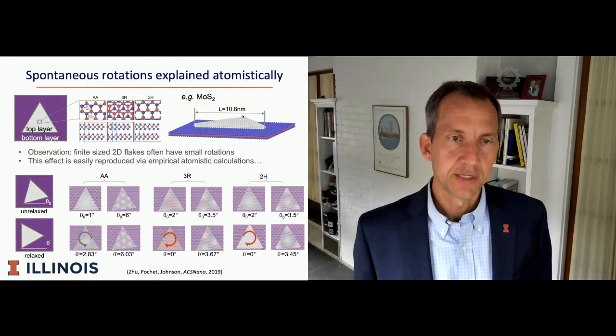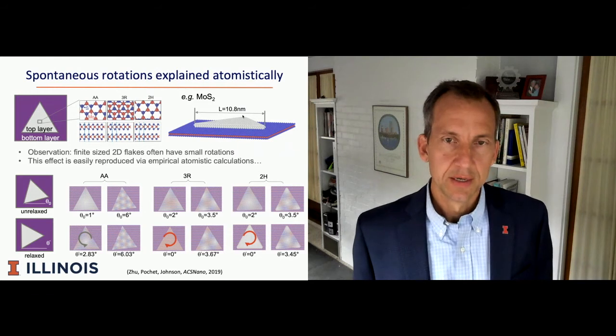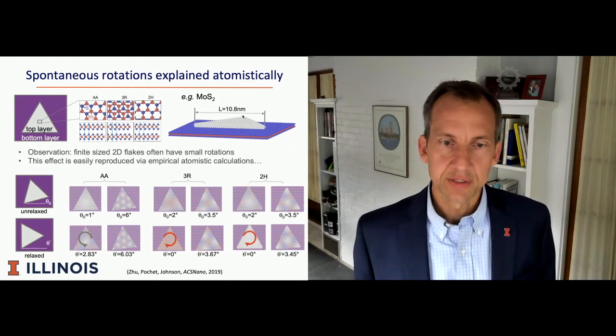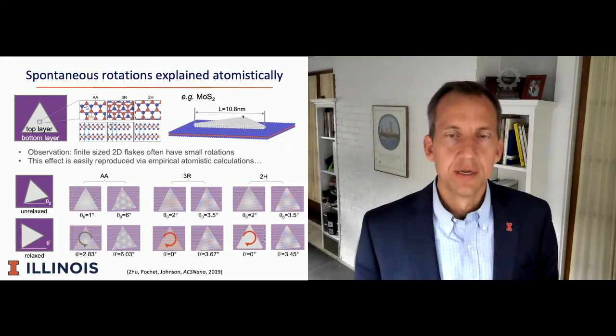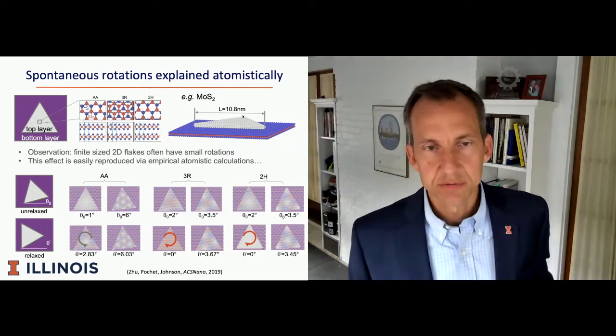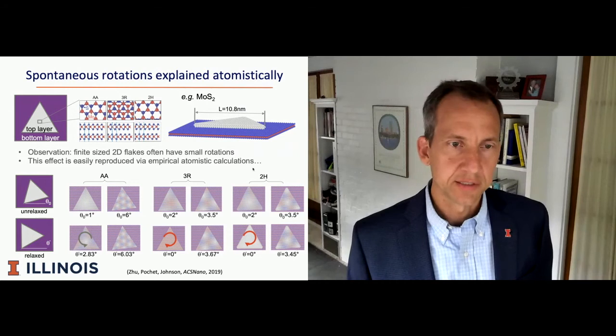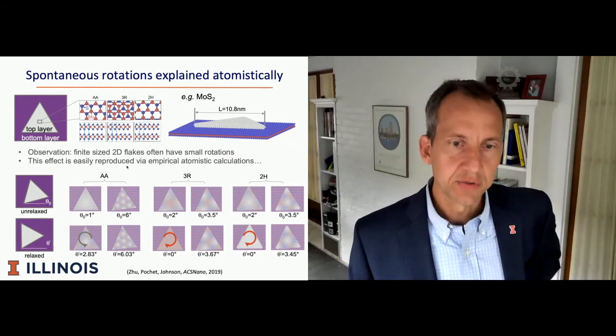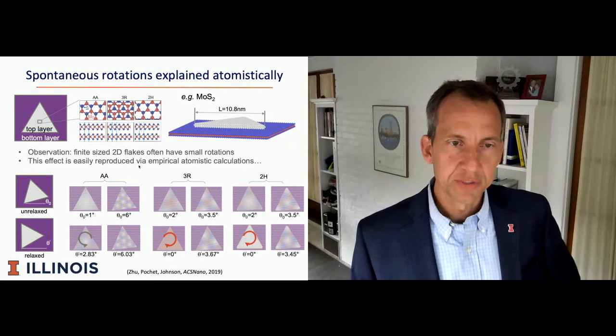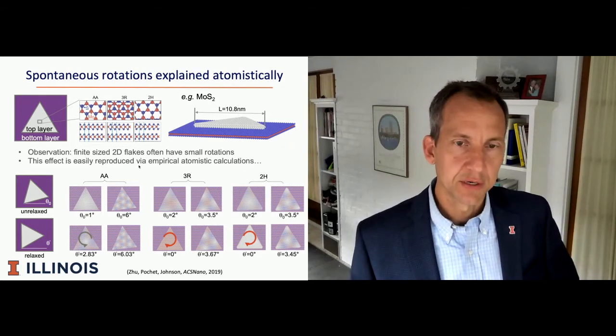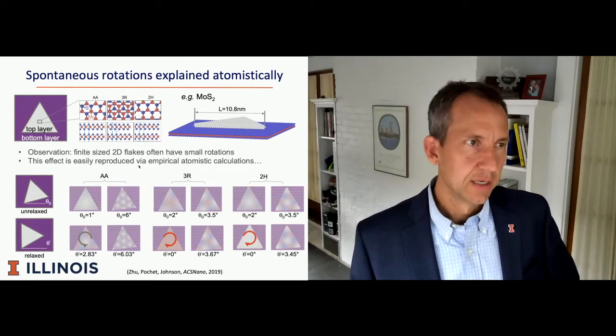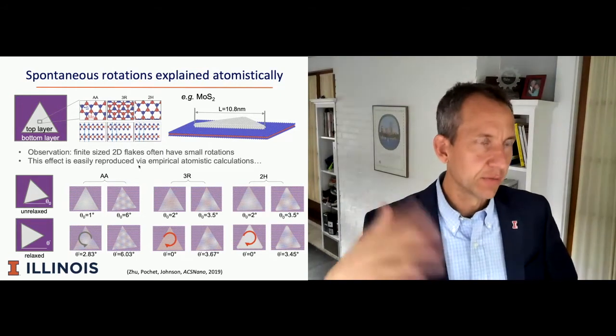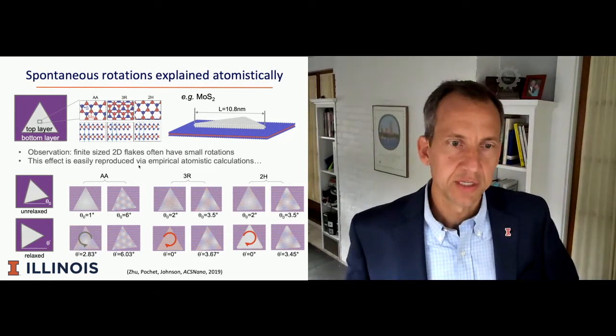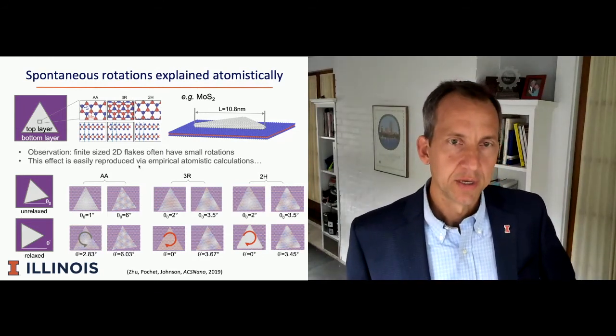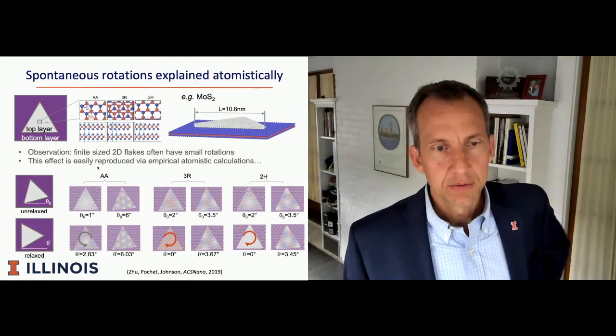We also know that when these are grown using chemical vapor deposition, the flakes tend to start with very tiny nuclei, and then they grow. And so the small size flakes are very relevant for understanding synthesis. So what we've done here is to use empirical potentials. We've used ReaxFF type potentials to model MoS2, and we've used a simpler interlayer potential to model the van der Waals interaction between the upper and lower layers. And we've done the following.